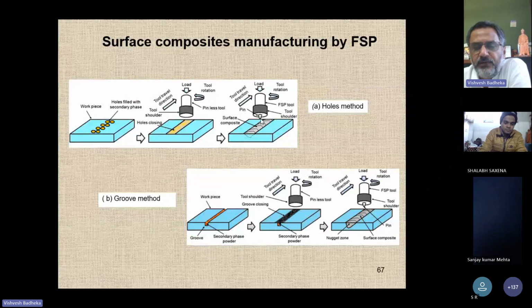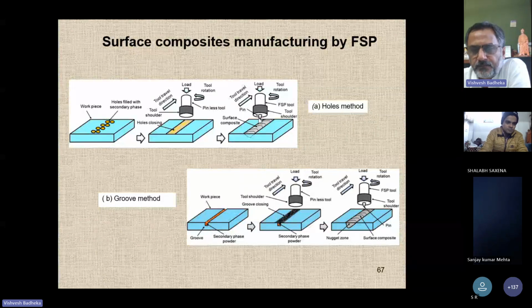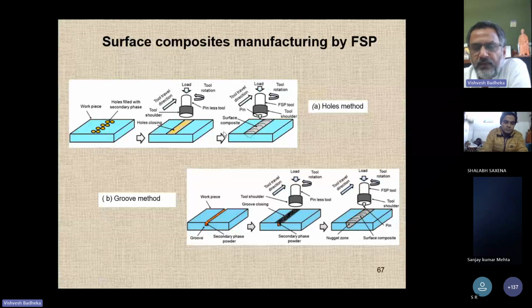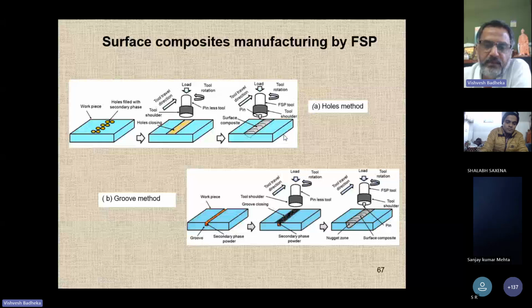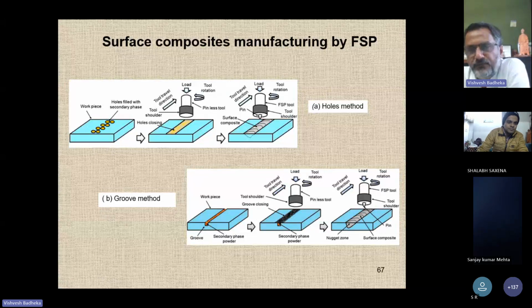Whatever the depth of the pin you have, say for example 3 millimeter or 2 millimeter, you will get the metal matrix only under that region, 2 to 3 millimeters. If you have a plate of 6 millimeter and a pin length of 3 millimeter, you are getting a metal matrix up to a depth of 3 millimeter, while the remaining 3 millimeter will remain as it is. So you have a sandwich property.